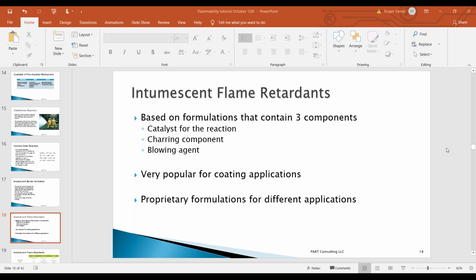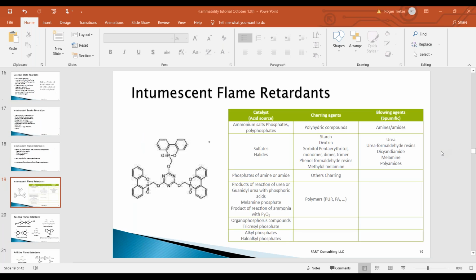Basically, intumescents are formulations, and what they need is a catalyst for reacting the charring component. The catalyst actually kicks off the blowing agent, so you get an inert gas. CO2 is the most common. And what will end up happening is that as it foams up, it creates this foam char layer. It's a very popular and effective agent for coatings. And there's many different proprietary formulations for many different applications. There are some drawbacks to intumescents, but they are very effective.